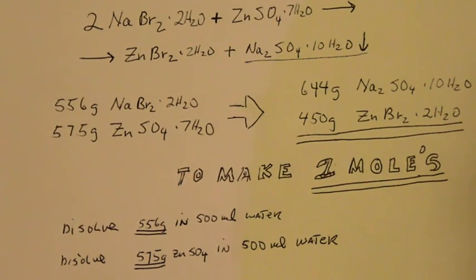You pour them together and then put them in a glass, say thirteen by nine Pyrex type dish, and put it in your oven and cook it overnight or whatever until you're down to about 200 milliliters. This will give you a 10 molar solution from one liter. Sometimes I have to do it in two steps because the Glauber's salt will fall out and you can scrape it out and keep going.